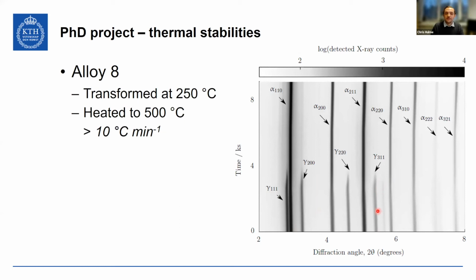And so what this experiment was, this was bainite that had been formed at 250 degrees until the transformation had run to completion. It was then heated at 10 degrees per minute to 500 degrees and held there until things stopped changing, at which point we then cooled it freely to room temperature.